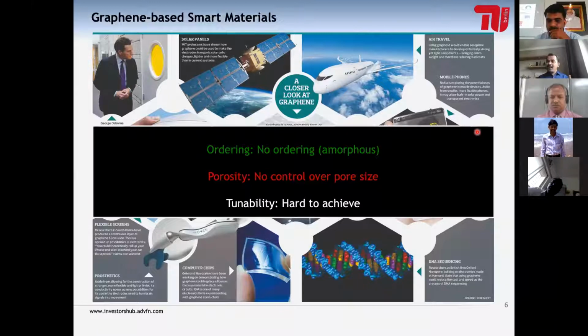The next part is porosity. We know that these materials have high porosity, but there are different kinds of pores. There could be macroporous, microporous, or even mesoporous, and they don't have tunability. For example, if I want a material having a pore size of, say, 2 nanometers, I can't synthesize exactly 2 nanometers or 4 nanometers or 6 nanometers, depending on the necessity of the application.